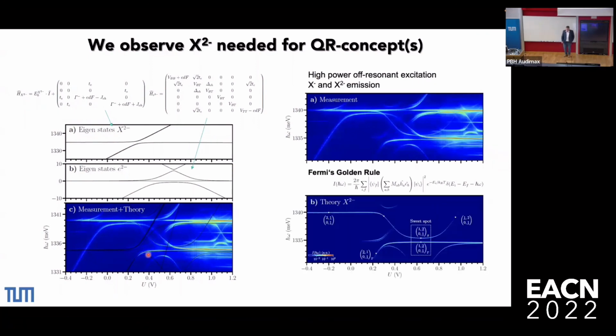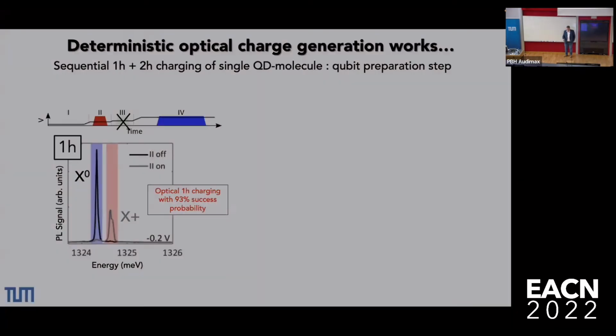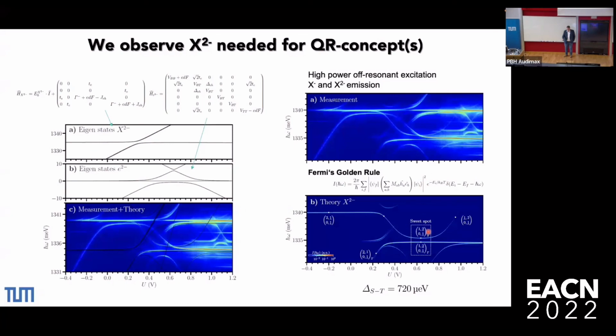To show that a bit better, there is the experimental data. There is then the theory of just this double negatively charged trion, and we can exactly extract, from this splitting here, from the sweet spot, the singlet triplet splitting. We find it's 720 micro eV. It should have been a bit smaller than this. It should have been 100, but this is an exponential function of the spacing between the two quantum dots. So we're currently growing samples where the spacing is a little bit larger, so we can suppress this tunnel coupling and allow us to control this molecule.